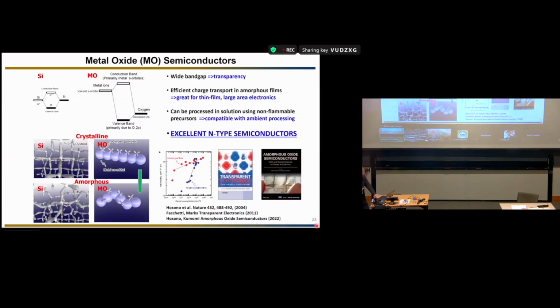Okay, now let me cover briefly another topic, metal oxide. So we are mostly interested in organic, but we've done quite some work on inorganic, particularly oxide. And we like oxide because these materials are optically transparent. Also, for many organics and for silicon, in order to get good charge transport, you need to have a crystalline phase, right? They have to be crystalline. But oxides, also in the amorphous state, have a very large electrical carrier mobility, so electrical conductivity, depending on the carrier density. Also, the other great advantage is that this material can be processed in ambient.